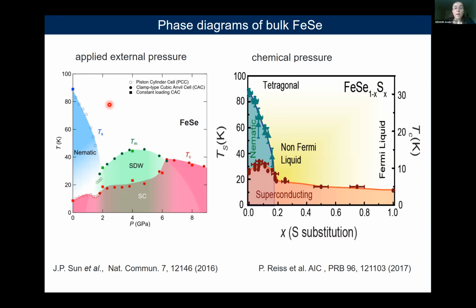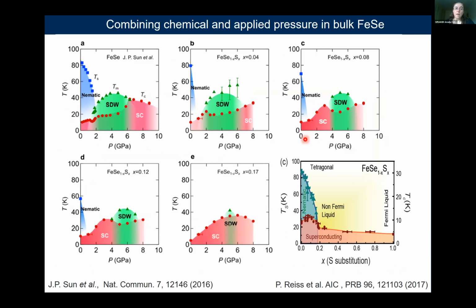So this is in contrast to what happens under applied pressure, where similarly one can see a nematic phase and a small dome of superconductivity at small pressure, but pressurizing further, the spin density wave magnetic order is stabilized. So it's living somewhere in the vicinity of this nematic phase, and together with this spin density wave, the superconductivity is enhanced by a factor of 4. So it's clear that magnetism has to play a role in enhancing the superconductivity in iron selenium under pressure, though no signature is seen with sulfur substitution. And by combining both chemical and applied pressure, we can tune these phases and reveal the position of the nematic critical points.